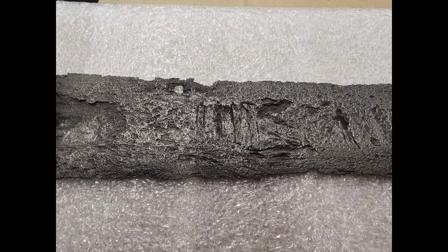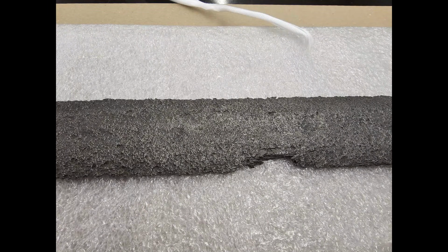Normally edge steel needs to be folded and welded at least 6 times back on itself to become of sufficient quality for edge steel, and it seems that this layer count is more or less also available in this particular sword. In contrast to the core billet and the edge steel, the outer surface panels do not show any signs of being refined by the fold and weld technique.